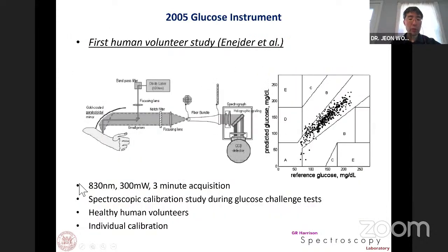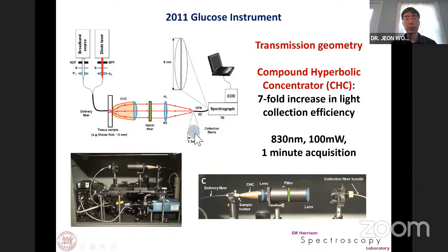So here we were using an 830 nanometer diode laser, and our illumination power was 300 milliwatt, and our integration was 3 minutes. So 830 nanometer is NIR, so typically you don't see the light, but 300 milliwatt and 3 minutes integration is still a lot of power. Even though we don't see much adverse effect, still many people don't feel comfortable when people are saying 300 milliwatt power will be illuminated to your skin during 3 minutes integration time. So we further improved the throughput of the system.